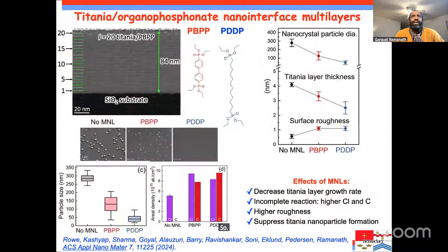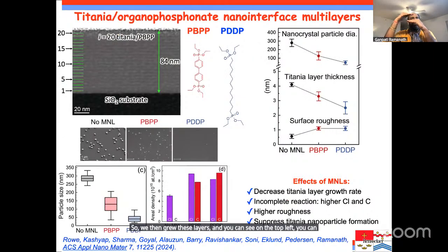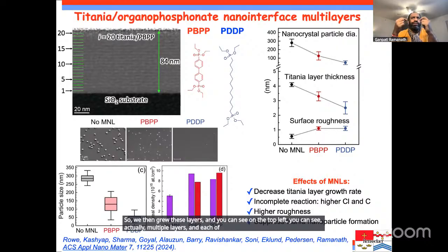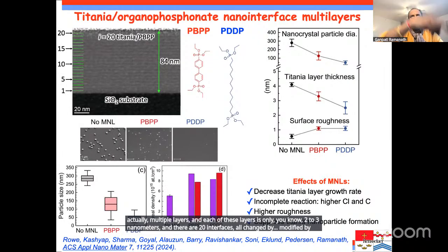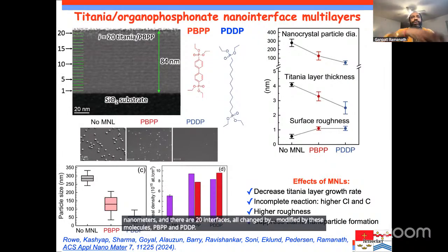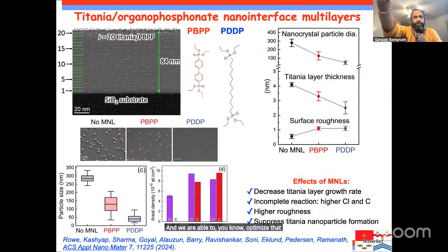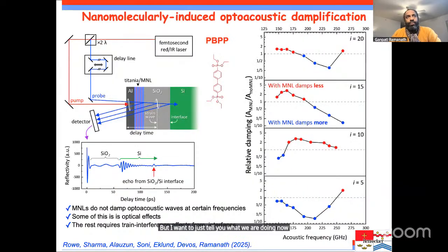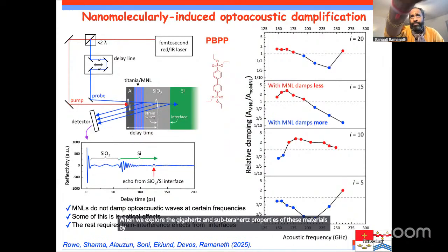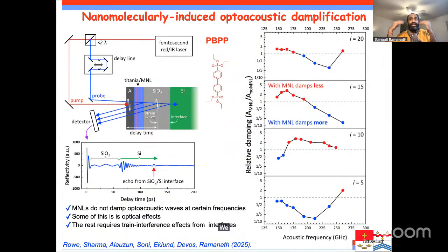So we then grew these layers, and you can see on the top left, you can see actually multiple layers, and each of these layers is only 2 to 3 nanometers, and there are 20 interfaces, all modified by these molecules, PBPP and PDDP, and we were able to optimize that, and this was a project in itself. But I want to just tell you what we are doing now. When we explore the gigahertz and sub-terahertz properties of these materials by pump probe spectroscopy, we find something very exciting.